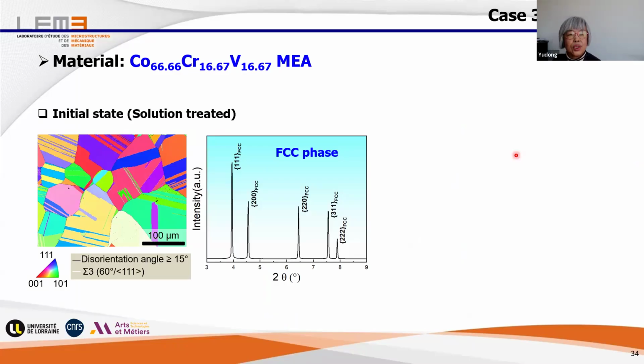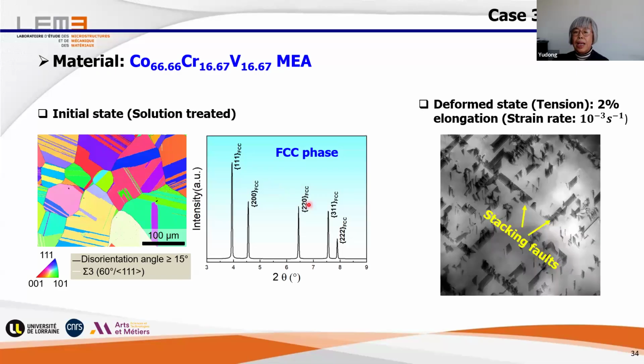Okay, and now I use an example to illustrate how we can use this software to guide our workflow of TEM operation. We also use the material, this medium-entropy alloy. With the initial state, we see these equiaxed grains with a lot of twins, annealing twins inside. We have a single FCC phase. And now we deform the material. In this application, I will show you how to identify Burgers vectors with this software.